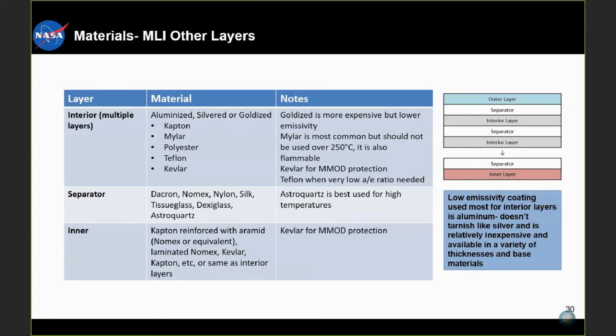So as mentioned, the other layers are the interior layers, the separators, and also an inner layer. For the interior layers, the material that's often used is aluminized, silvered, or goldized Kapton, Mylar, polyester, Teflon, or Kevlar. Some notes: goldized is going to be ultimately more expensive, but it does have a lower emissivity. Mylar is actually going to be the most common, but it should not be used over 250 degrees C, and it also is a flammable material.